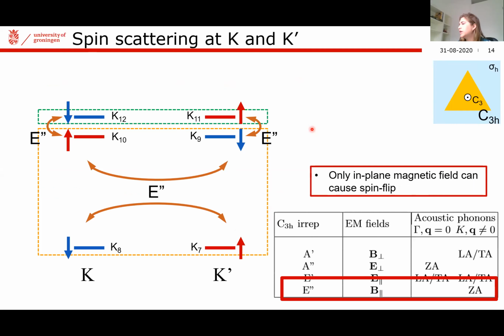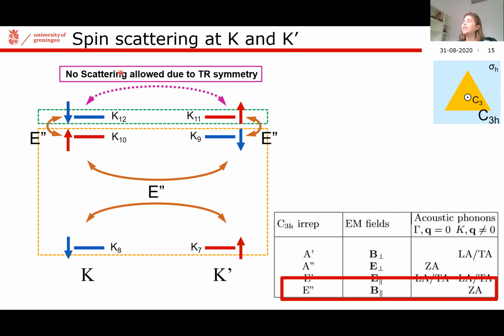Now we can also go and check what type of operators are those, and that is actually a magnetic field in the plane of the monolayer. So only magnetic fields in this plane are actually able to flip the spin. What you should notice also is that I drew no arrow here between K11 and K12, and that is because since these states are each other's time reversal partners, there's no scattering allowed between them. This scattering is protected by time reversal symmetry.